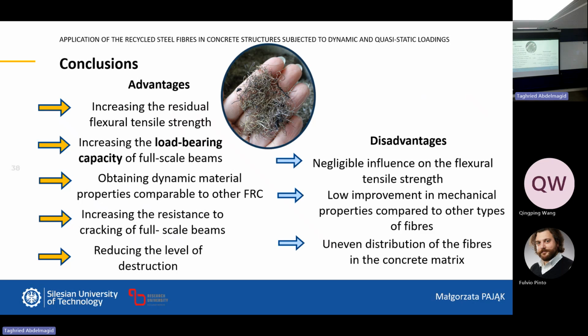And disadvantages. So negligible influence on flexural strength. So this is a disadvantage, because when we have the normal hooked fibers, it always increases the flexural tensile strength. But there is nothing we can do about it. And this low improvement, it is low, but it can be considered. So we can't say to someone who is buying it that you will get the composite with the high values of tensile strength. You will get the composite with enough, let's say, tensile strength, and uneven distribution of the fibers. But we noticed it in concrete, now in the self-compacting concrete. So it is worth pointing out.